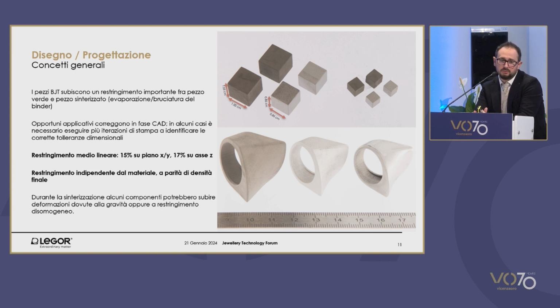The item is 15% larger when I'm printing it compared to the final item on the x, y plane and 17% on average on the z-axis, which is the axis on which the binder is deposited. So if the object has been perfectly sinterized, these parameters are independent of the type of alloy. So the size monitoring in terms of size prior and after sintering in steel, platinum, and silver is an independent value, at least if we consider powders that have been atomized in inert gas. This is the ideal case, so once you decide the size, I can proceed with the production.